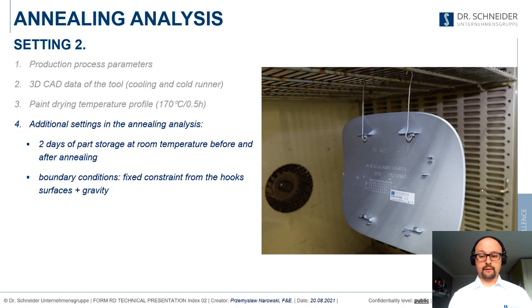We can just make our model more complex. This is what we usually do for our simulations, for our cases. We just introduce additional boundary conditions, additional information into our input data. And so we did in this case. We tried to make the annealing analysis more accurate. For that reason, we changed the temperature profile. We introduced 2 additional days before and after the annealing, because the part isn't just directly taken from the injection molding machine after the injection and painted. It stays a couple of days in the warehouse, and it isn't, of course, directly measured after the drying and the painting process.